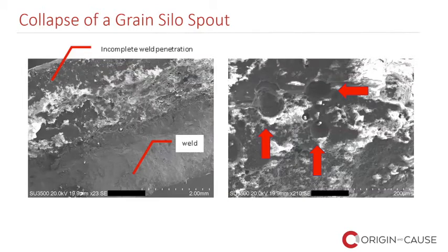The fractured weld was taken for examination under a scanning electron microscope, and again, relevant features which were not necessarily visible by the naked eye were observed. On the right image, you can see the weld has a lot of pores, and in the left image, the incomplete weld penetration was confirmed. Porosity, not only in welds, but in every material, is an undesirable condition because pores can act as stress concentrators and they can reduce the load carrying capability.